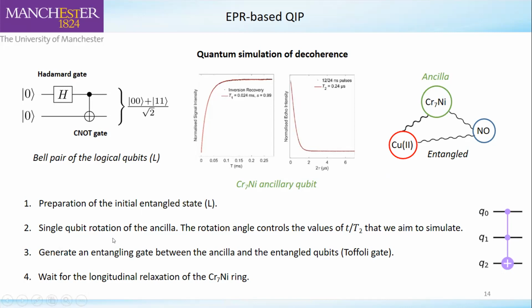We can then do a single qubit rotation of the ancilla, which in this case will be our chromium-7 nickel ring, because this is the spin that relaxes very, very fast. So this is going to be the spin that actually simulates the decoherence on the entangled states of the copper and the nitroxide. And the angle of the rotation of this spin is going to control the decoherence values that we actually want to simulate in this system.